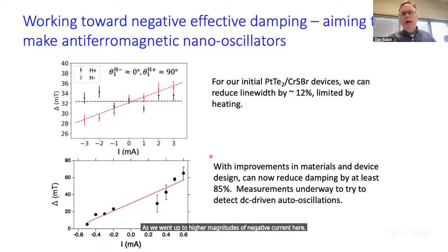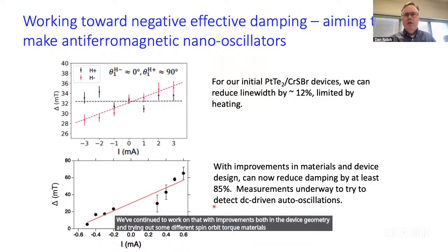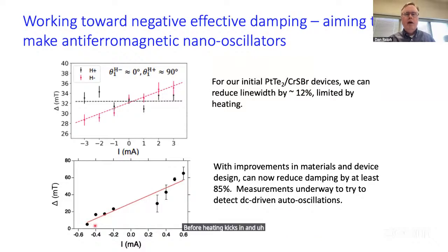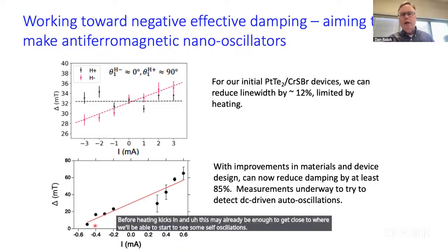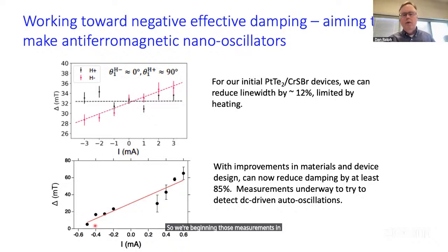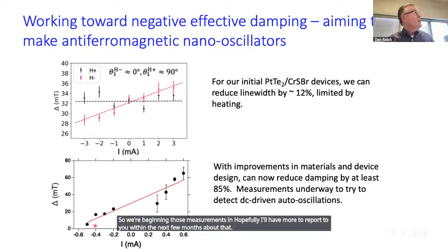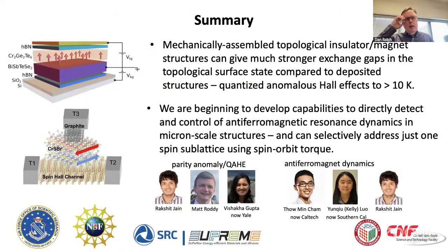We've continued to work on that with improvements both in the device geometry and trying out some different spin orbit torque materials. Our best result from last week now is that we can actually modulate the line width by at least 85% before heating kicks in. And this may already be enough to get close to where we'll be able to start to see some self-oscillations. So we're beginning those measurements, and hopefully I'll have more to report to you within the next few months about that. Okay, so that's the stories I wanted to tell.